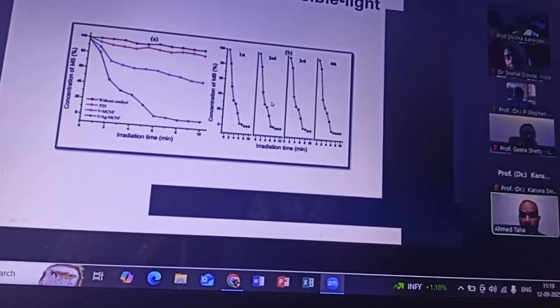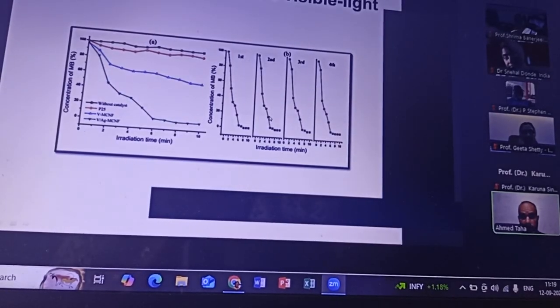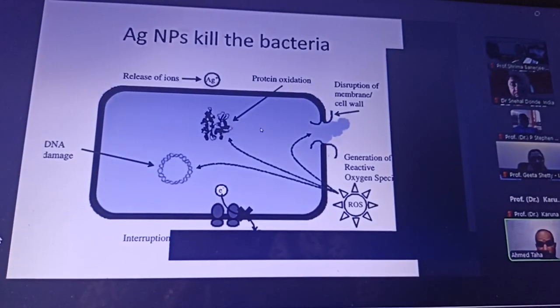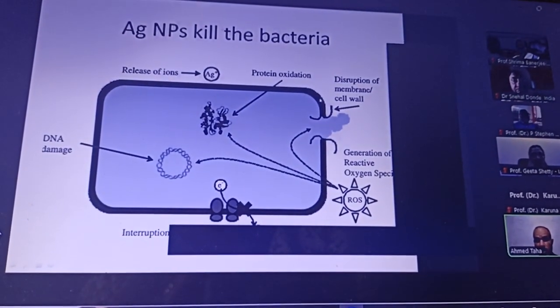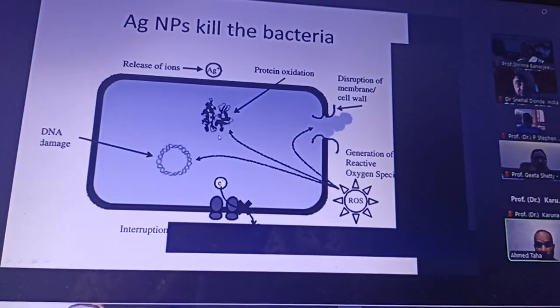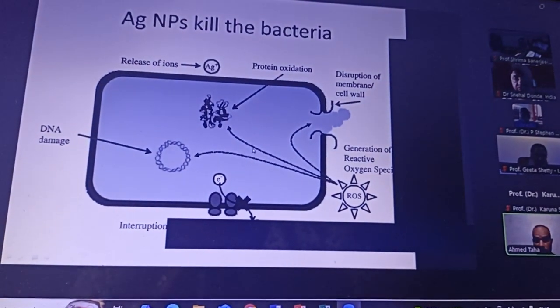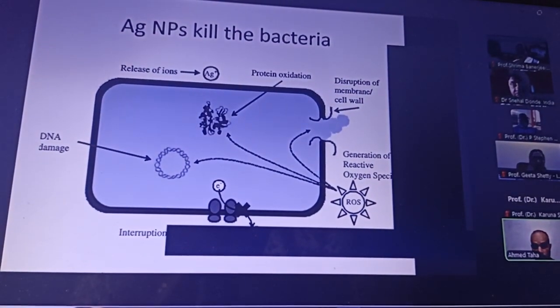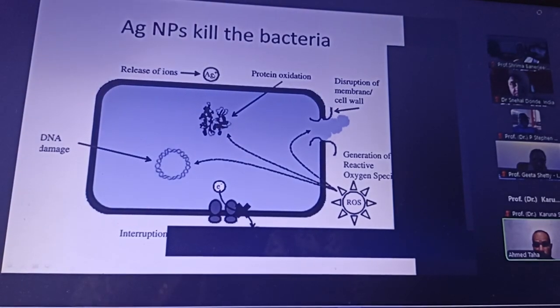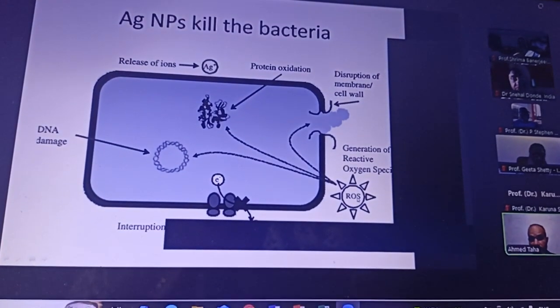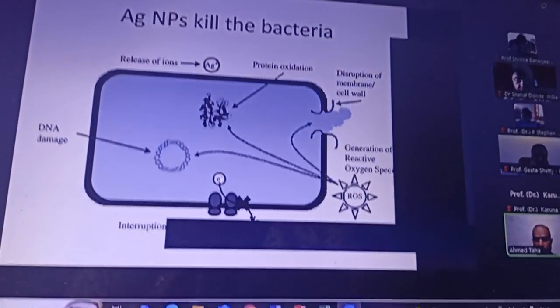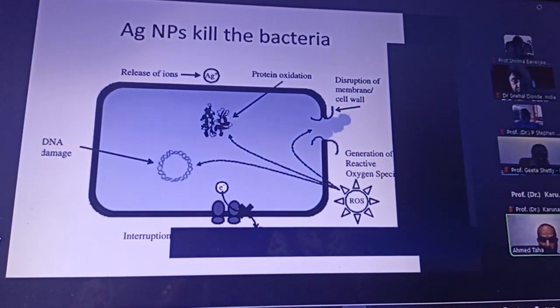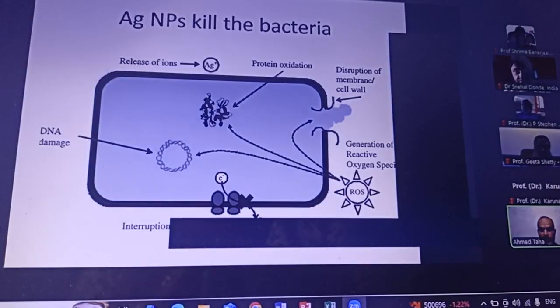So this is the dye removal. Within minutes, we can get rid of these dyes, and we can recycle the material with stable and good performance. The disinfection actually happens mainly by the silver, which travels to the surface of the membrane of the cell, breaks it down, gets into the cell and damages the nuclei of the cell, and the cell then dies. So silver plays one role, and also, if you remember with me, the radicals that come out from the catalytic reaction also play a role in killing the bacteria.